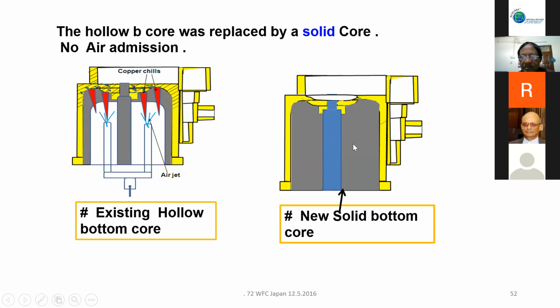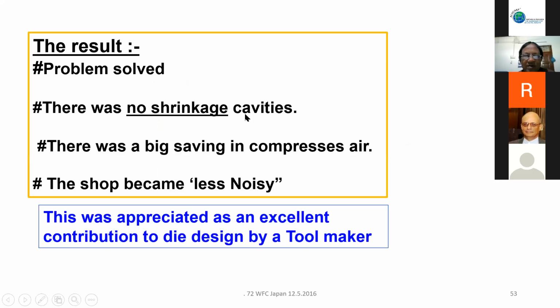So it's a new one. We tried this core and found no shrinkage at all, because the heat conduction was very fine. No air, no sound. And this was an excellent idea from a tool maker. It goes from bottom to top. And his idea was well taken by the die design people.